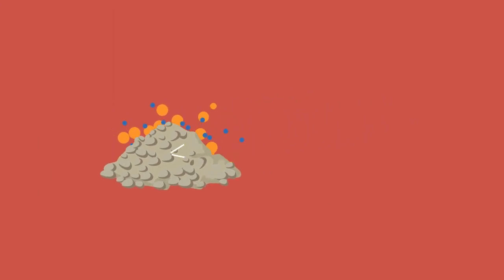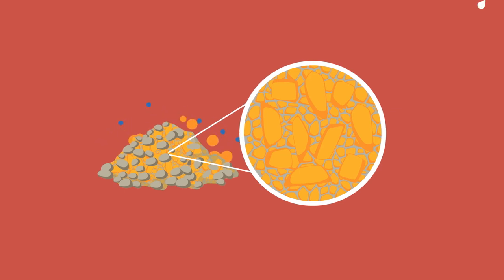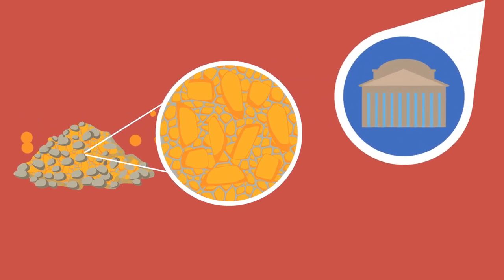This problem can be partially mitigated by adding sand and aggregates to produce mortars and concrete. In doing so, one seeks to maximize the amount of sand and aggregates in a mix by optimizing their grain size distribution to allow the smaller particles to pack within the gaps left by the larger ones. This is also something that the Romans had well understood and optimized for.